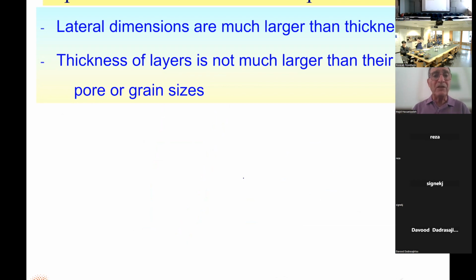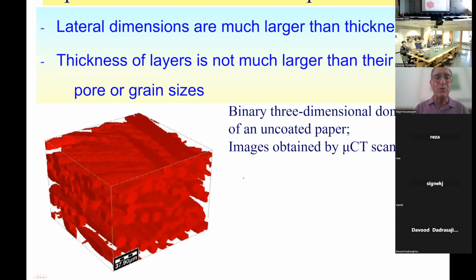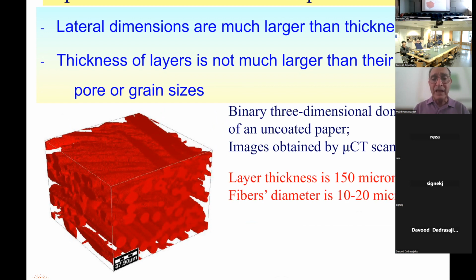Now, another aspect is that, as I said, the lateral dimensions are much bigger. You have a thin porous medium. So for example, here you see that the size of this layer is 150 micron. And the fibers are 10 to 20 micron. They are not much smaller than the thickness. So the question is, can you really treat this as a continuum and use macro scale models to model flow through this by discretizing this layer?